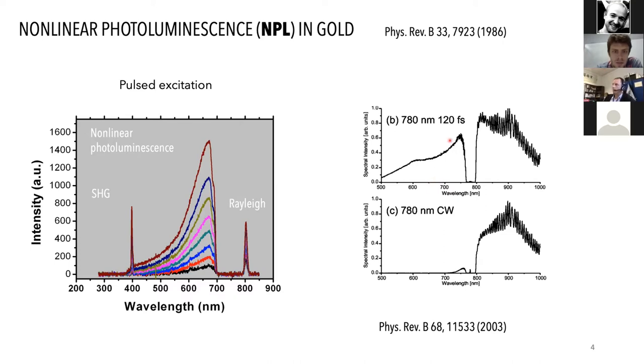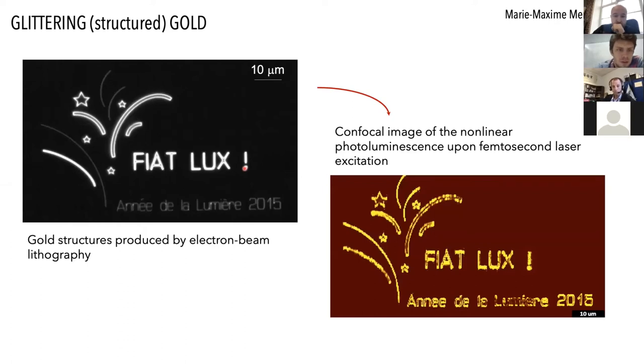And this shows the difference between a pulsed excitation and a CW excitation. You can appreciate that this nonlinear photoluminescence spanning the entire visible region is only there when you have a pulsed excitation, when you have this high peak intensity laser. And it's completely gone when you have a CW steady-state excitation. Interestingly, there is also a large photoluminescence background on the Stokes side of the excitation. Again, I'm not going to be talking about this today. You just have to know that this is also photoluminescence coming from the gold. This one goes linearly with the excitation. In the remainder of the talk, we'll be mainly focusing on this up-converted radiation, which has a strong nonlinear dependence on the laser intensity.